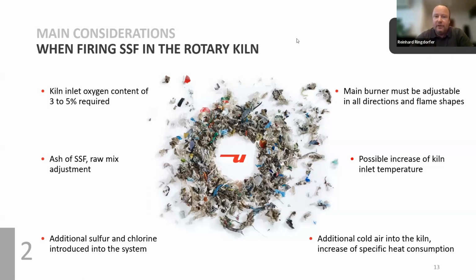Of course, you have to have a main burner which gives you all the freedom you need to adjust in any direction. And you also have to consider that you're introducing additional moisture into the kiln, which needs to be evaporated. You're introducing additional cold air because of the pneumatic transport, which can or will increase the specific heat consumption of your process.